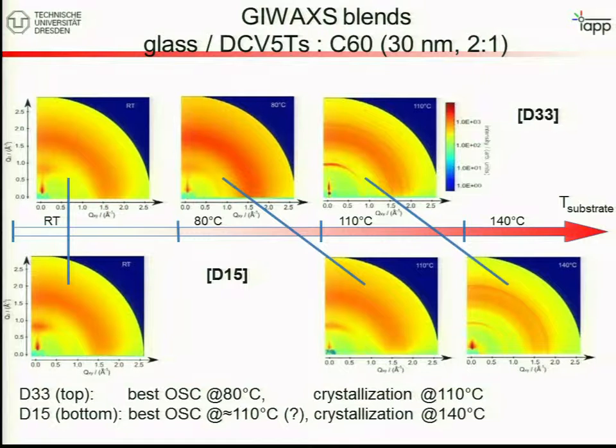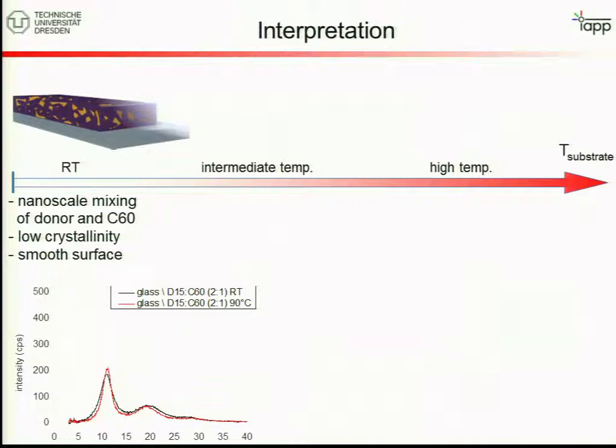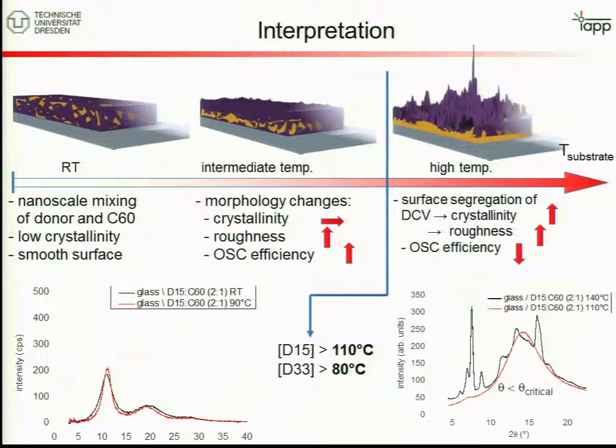So the message is that it's very, very time consuming to test these organic materials, because for every molecule you have to optimize the conditions. In silicon or CdTe, you do that once in a very basic picture, but in the organics, every molecule is a fresh start, and that is very time consuming and one of the big difficulties of the field. And due to lack of time, I won't really go into the details, but there's a very complicated behavior of morphology, domain size, and roughness as a function of thickness, which we still little understand.